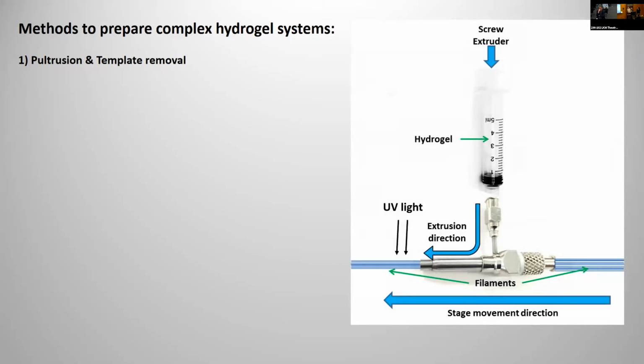This setup here is what I developed. And as you can see along the bottom, I'll try not to point too much because I know people can't see what I'm looking at. So these fibers are first threaded through this needle setup. So it can be anywhere from 5 to 16 fibers have been threaded through this. And then the hydrogel is pushed down and extruded out around those fibers while the whole setup is moving along a stage and being cross-linked as you go.